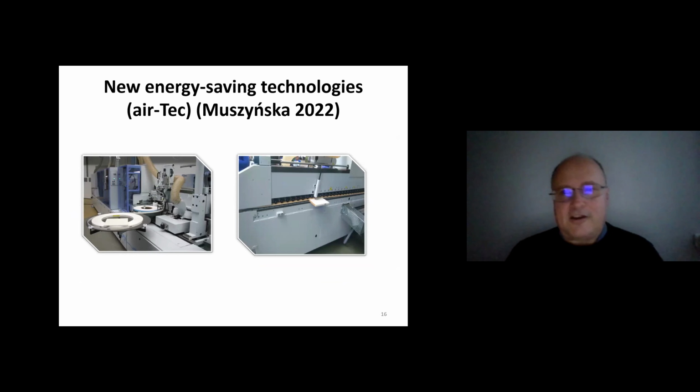And going to new technologies, my PhD student, Monika Muszyńska, finalized a PhD using different new energy-saving technologies. Because when we use hot melt adhesives, we need some energy, high temperature for melting, minimally 140 Celsius, and maximally more than 200 Celsius.